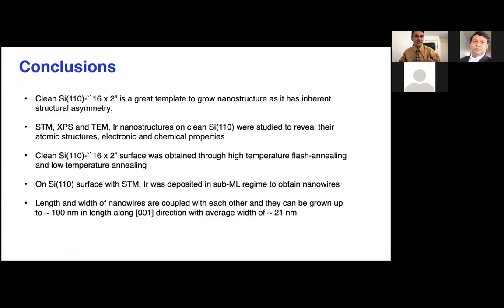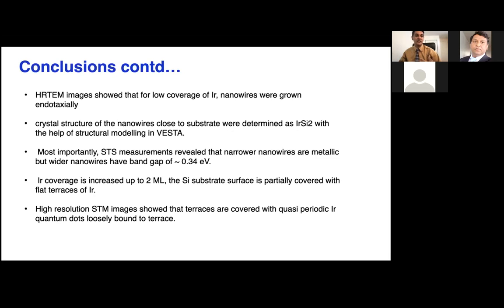Actually, for the conclusion, I mainly used clean silicon 110, which has a 16x2 structure. That's a great template to grow nanostructures. In this experiment, I used STM, XPS, and TEM to study the chemical properties, electronic properties, and cross-sectional structure. We have to anneal the surface at lower temperature after the flash annealing. High resolution images show that a low coverage of iridium tends to grow nanowires on the surface. This kind of growth we call endotaxial growth.